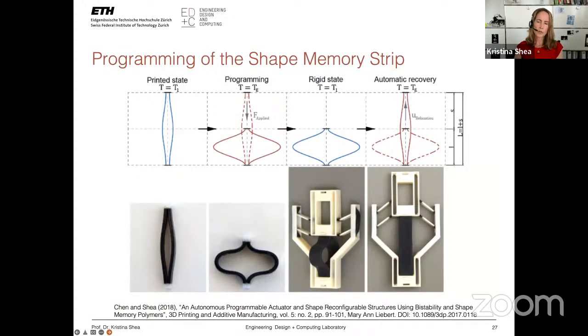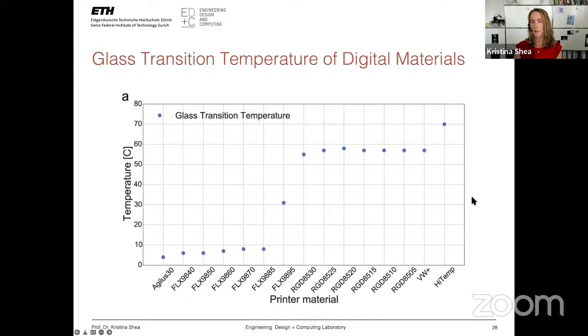And so the work we do uses the shape memory polymer quality of the Connex materials by a programming model. And so the programming of a shape memory strip is different than computer programming. What you have is a printed state, and then you heat it to the glass transition temperature, you apply a load, and then you cool it down in the third step. And then the final step is to recover it by heating it back up. So it's a very simple so-called programming process, but it's programming of the material.